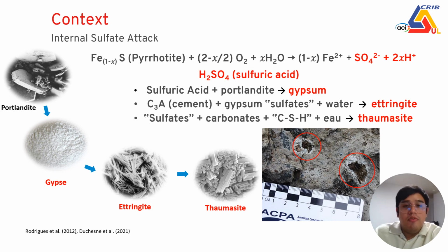So after the oxidation process is done, the iron sulfide mineral will continue releasing sulfur, and this sulfur will transform into sulfuric acid that will attack portlandite to transform it into gypsum. And if we have water and an alumina source from the cement paste, the C3A, it will transform into ettringite. And if we have the ideal conditions, like a source of carbonates, the silicium from the cement paste, and more water, we can form thaumasite. And thaumasite is a really destructive mineral for the cement paste. You can see here in the picture a concrete affected by this reaction. Normally, there will be a whitish color around the aggregate. We say O-ring, and this O-ring is an indicator that several internal sulfate attacks have already happened on the cement paste.